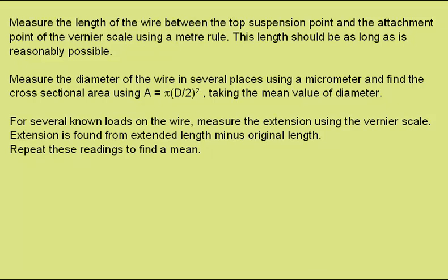For several known loads on the wire, we need to measure the extension using the vernier scale. Extension is found from the extended length minus the original length, and we must repeat these readings to find a mean.